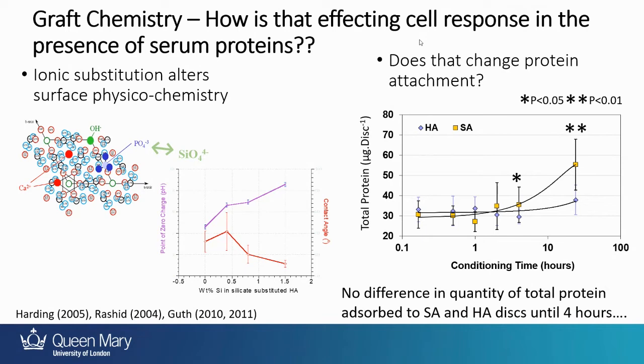So it's also affecting the contact angle. So if you compare a frying pan with PTFE coating on it versus a frying pan without a PTFE coating, and you drop a bit of water on there, you get the water bubbling up on the one with PTFE, and that's because it's hydrophobic. So what you want to do is reduce that, you want something to become more hydrophilic in something like bone graft substitute, because you want the surface and the proteins to interact on that material. So we found as we were changing the chemistry, we were also manipulating the contact angle and the surface charge, and thought, okay, so that must be what's affecting the proteins.